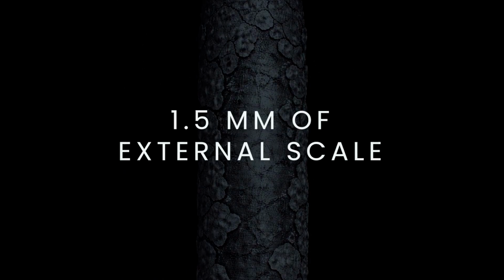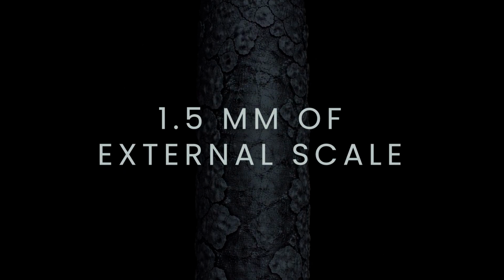Now, in another example, tubes were found with approximately 1.5 millimeters of external scale. Think 60 mils. Now, from a heat transfer standpoint, that's extremely costly. Think about a clean carbon steel tube, which has a thermal conductivity of roughly 16.8 BTUs per hour per square foot per Fahrenheit. So 16.8.